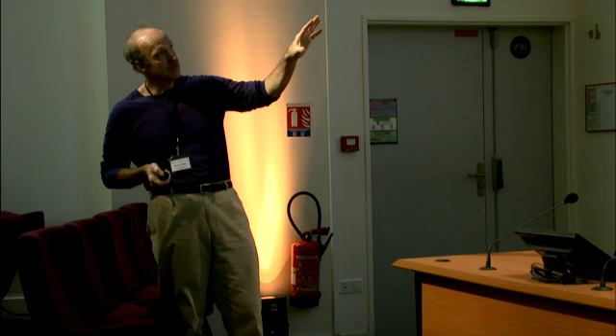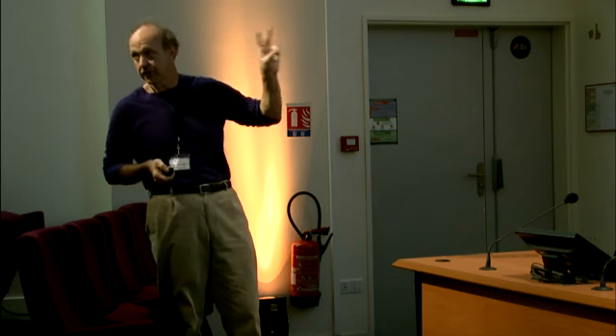Okay, and then this one, we can't go to the next closed shell here, which would be 309 atoms. We just can't make particles that big inside this dendrimer. And so instead what we look at is a 225 atom particle, which is a magic number for a truncated cubo-octahedron. So it's a slightly different structure. And now, here again, you see quite a bit more charge, consistent with the higher surface area on that platinum particle. When you just look at these cyclic voltammograms, there's 2 things that you notice.